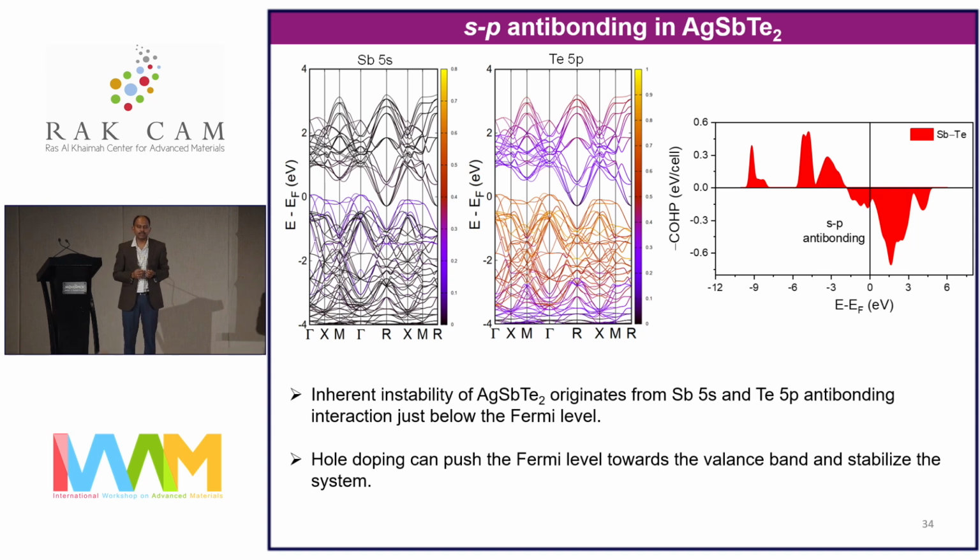So you can see this is the electronic structure of this AgSbTe2. The valence band is generally formed by, surprisingly, tellurium p orbital and the interaction of 5s2 lone pair of antimony. That also hints that the antimony lone pair is locally stereochemically active, and we have evidence from synchrotron X-ray PDF data. I'm not going in that direction today. So locally, the antimony expresses the lone pair and distorts the crystal structure, but globally, the structure is basically rock salt structure.